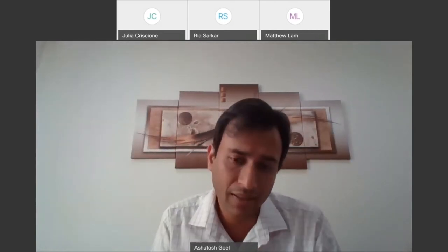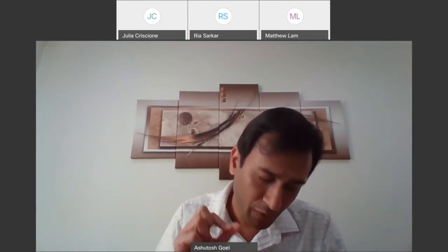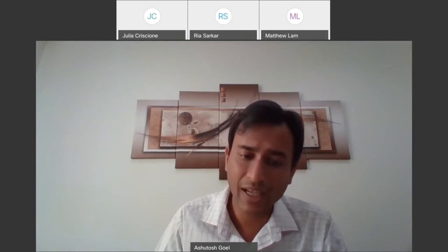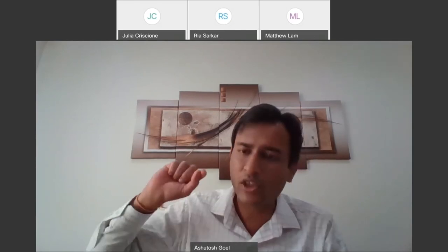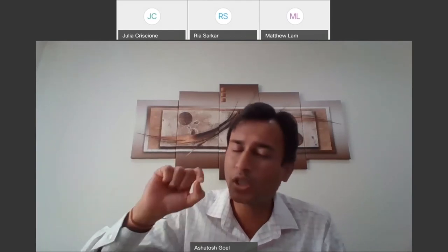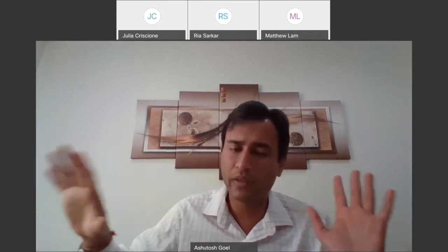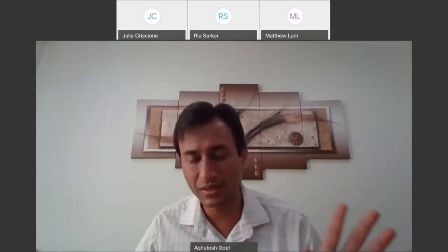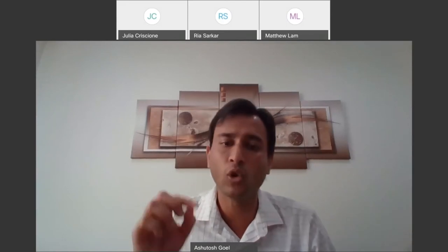No, that's incorrect. There has been research done by a professor from Brazil, Professor Edgar Zanotto. He has shown in his research that for even normal window glass to flow just 1 centimeter at room temperature, it will take more than human existence on this earth. It will take probably millions of years for glass to flow even 1 centimeter.